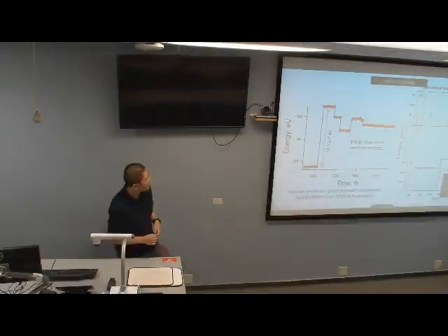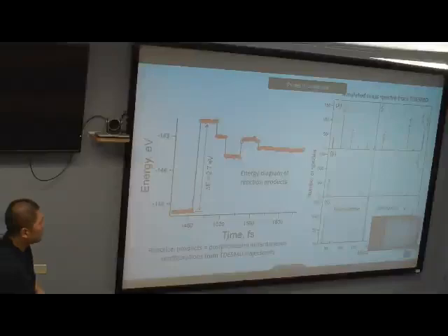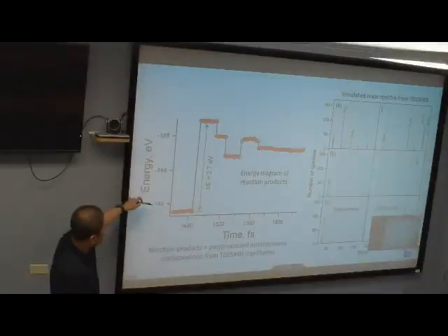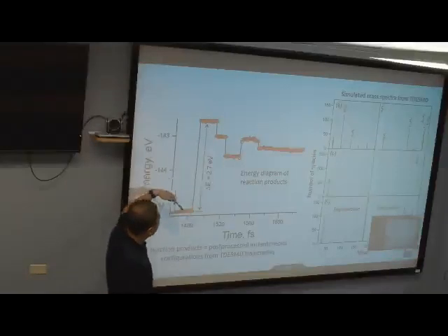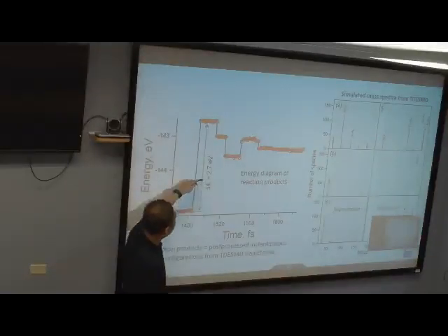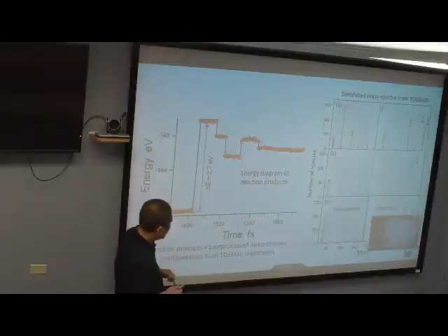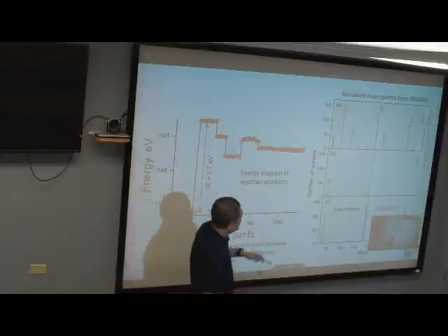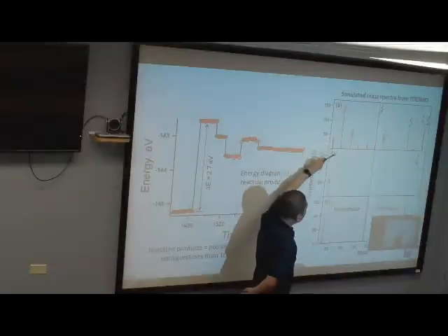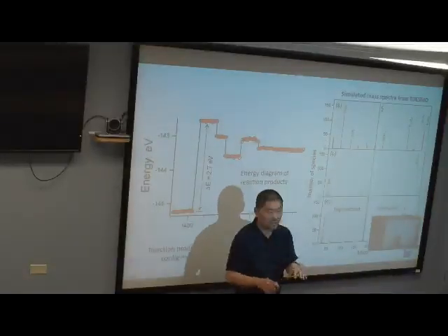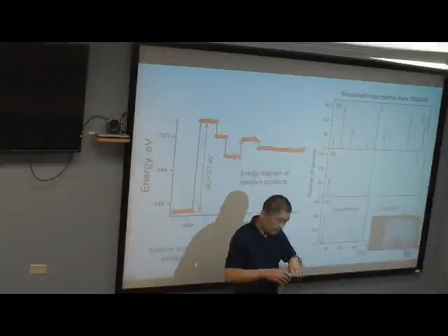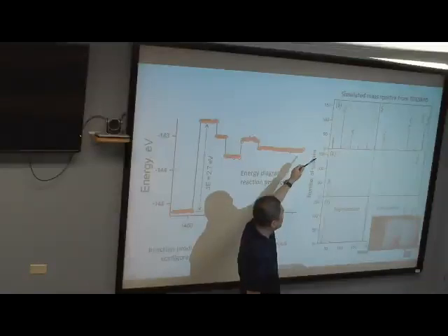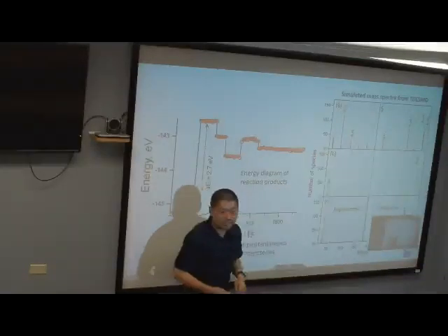This is another set of data we can get from TDSMD trajectory. This is an energy profile. We can see the activation energy for this kind of dimerization reaction is about 2.7 electronvolts. We can also get the mass spectrum from TDSMD trajectory. And these are different spectra corresponding to different starting points for TDSMD calculations, as well as different excitation conditions.